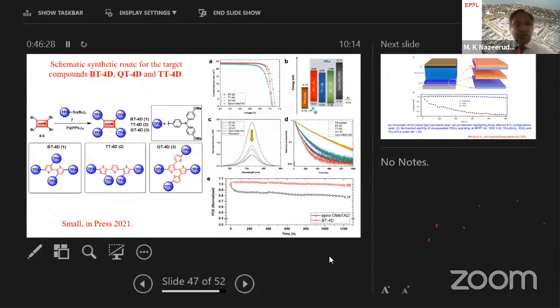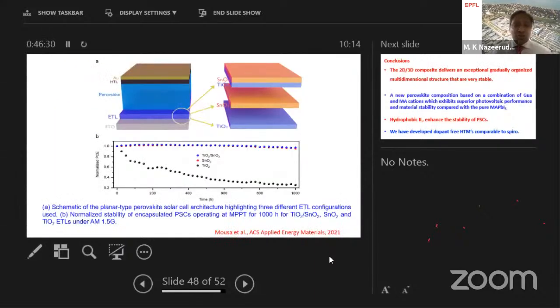So the next slide shows the electron transport materials. Here is the data based on three different types of electron transport materials. On the bottom, that's the black line. It shows the stability data of our perovskite solar cells when we use only TiO2 as the electron transport material. However, if we change the electron transport material to pure tin oxide, the data is buried under the blue lines. So it's extremely stable.